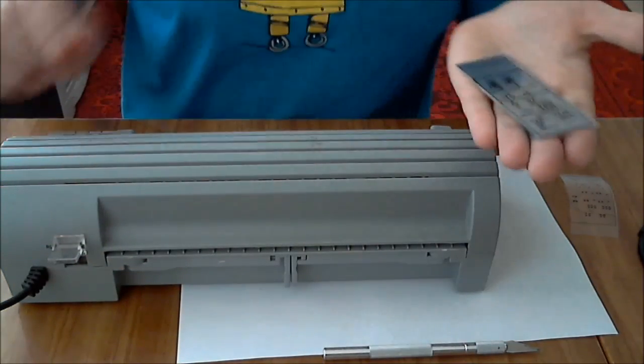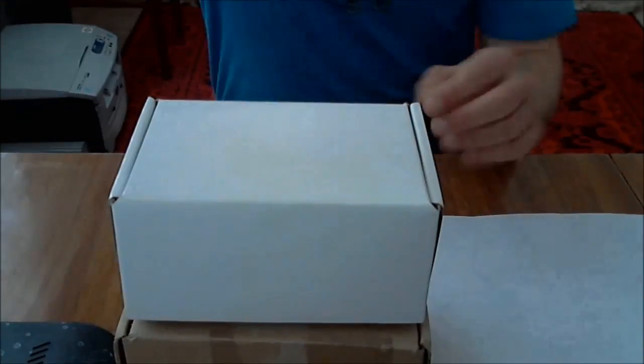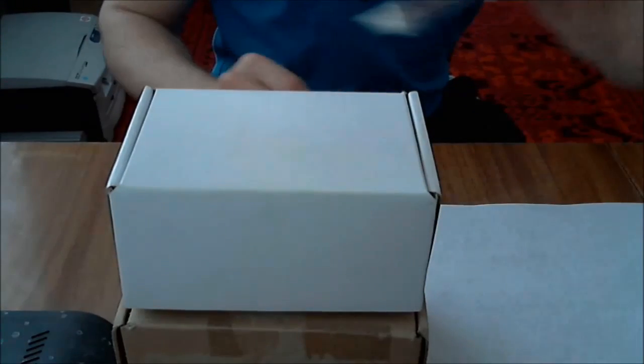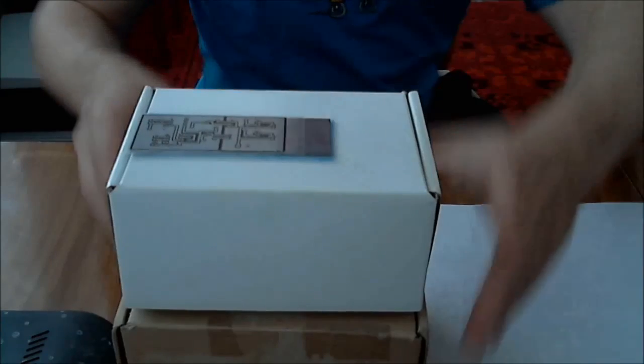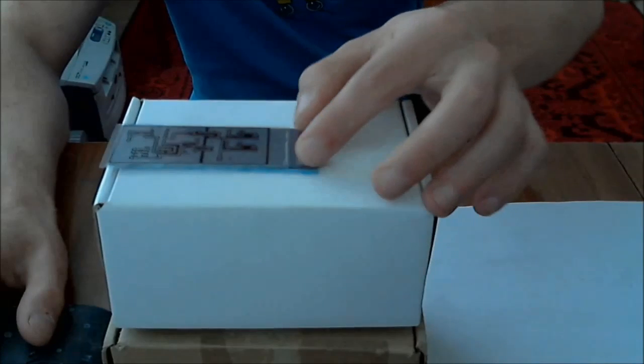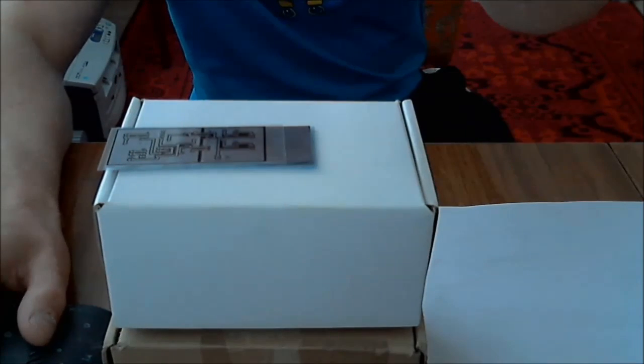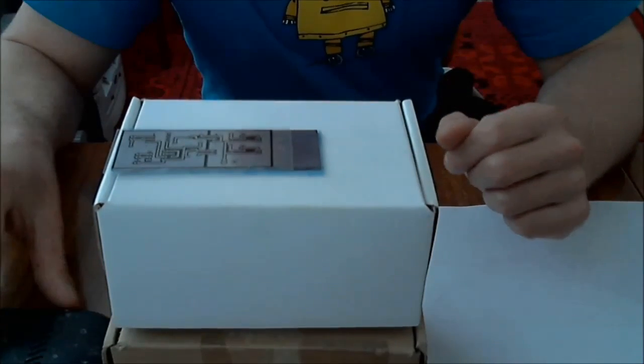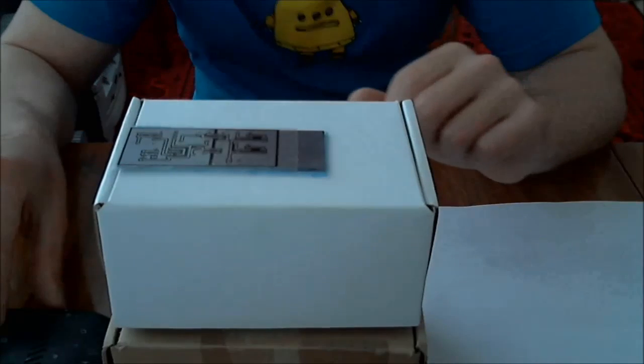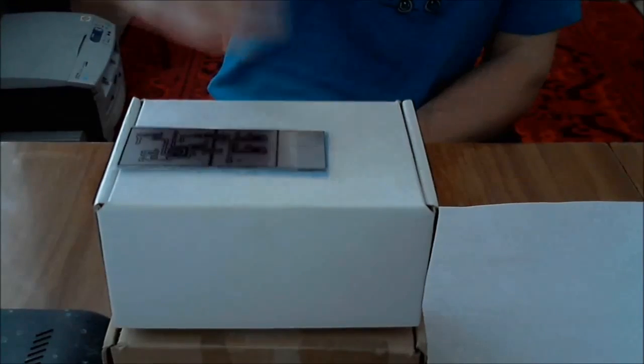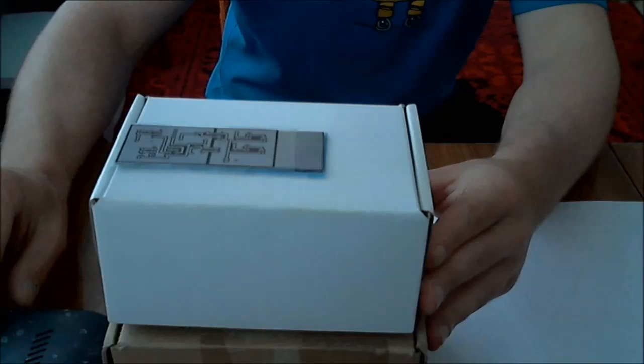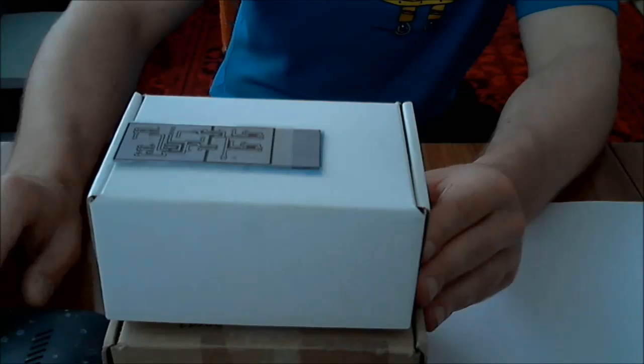So the next step is exposure. I got my UV lamp right here and a little stack of boxes to keep the distance right. I'll put the PCB right underneath the UV lamp. I'm using just one 9-watt UV light bulb, so I'm trying to keep the distance around 6 to 8 inches to provide even exposure all across the surface of the board. We'll just put it here and try to expose it for around two minutes, two and a half minutes. If you're using sunlight, you should probably keep it as low as 60 to 80 seconds.